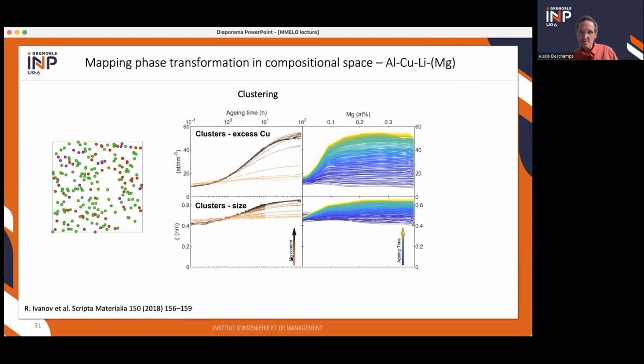And when you look at this composition gradient in magnesium, you see that the magnesium concentration does not change much the size, but when you go from one composition to another, you have kind of a jump in the cluster kinetics. So the clustering kinetics is quite slow when you have no magnesium, and suddenly it becomes very, very fast. And this happens for quite small amounts of magnesium, actually less than 0.1%.